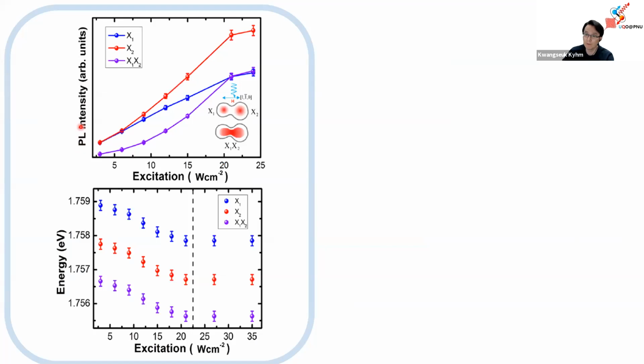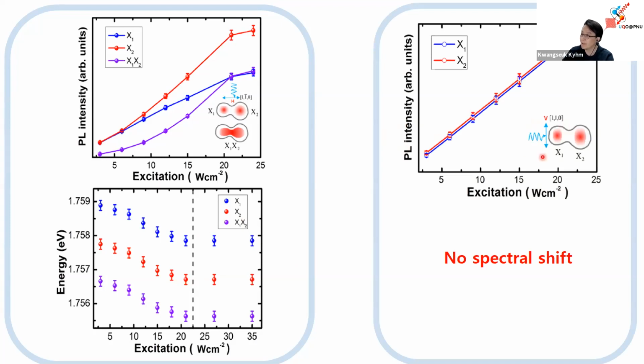We also analyzed photoluminescence intensity as a function of excitation power. The blue one is from the small quantum dot, high energy, and the red one is the exciton from the large quantum dot, X2. With increasing excitation power, the luminescence increased, but the blue one becomes saturated while the red one shows a superlinear increase. At the same time, the coupled biexciton is also increased. That suggests there is population transfer from the blue, high energy, to low energy. We also plot the redshift when the excitation is H-polarized along the coupled direction. On the other hand, with V-polarized excitation, there is no such thing. Luminescence intensity is always balanced, even if you increase excitation, and there is no spectral shift.